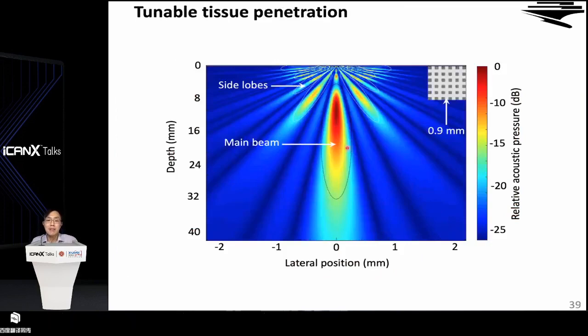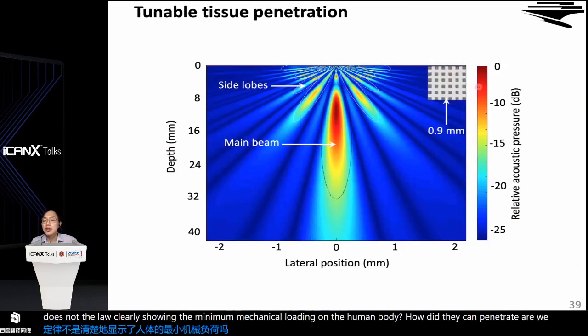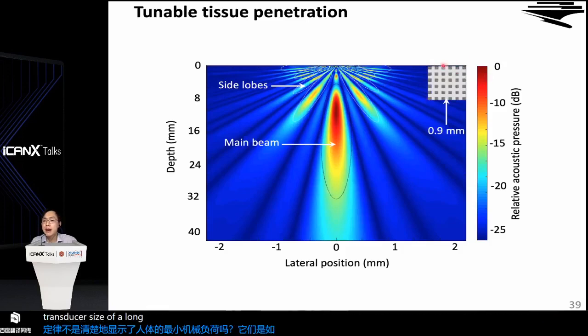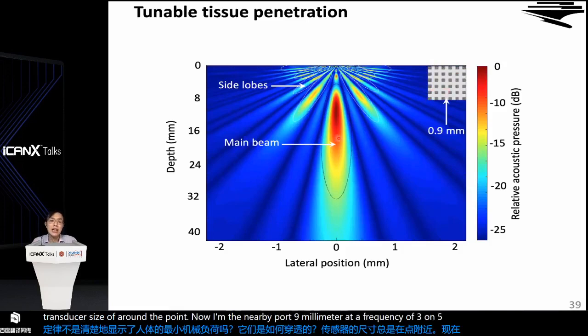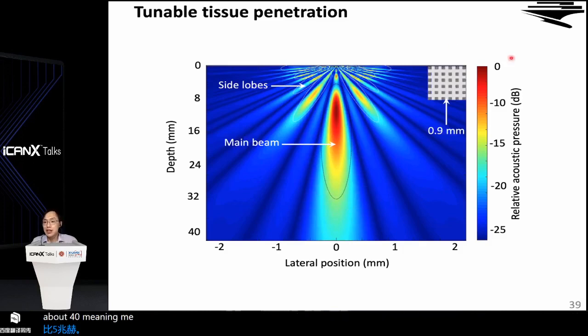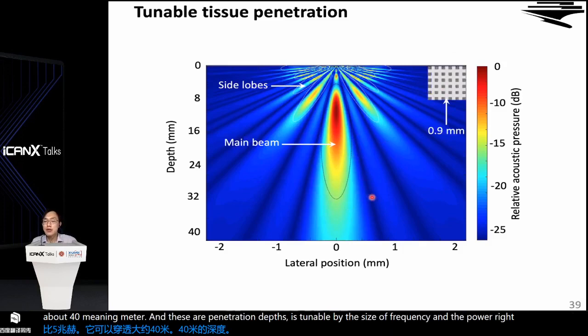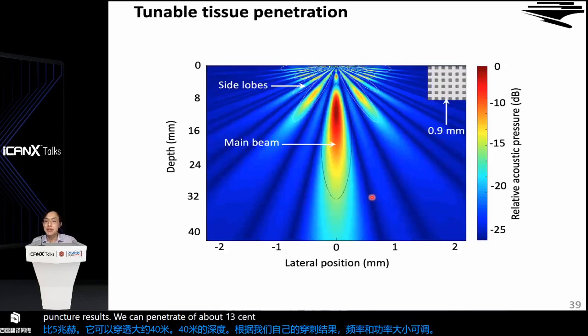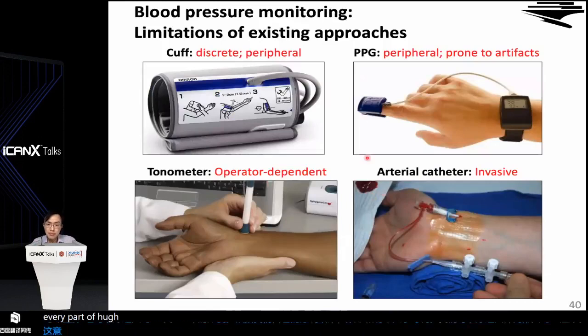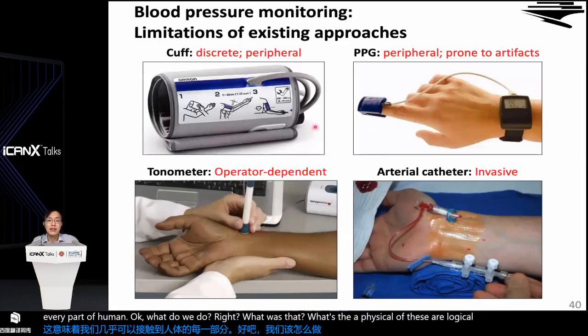How deep can the ultrasound penetrate? With a transducer size of around 0.9 millimeter by 0.9 millimeter at a frequency of 3.5 megahertz, it can penetrate about 40 millimeters. And this penetration depth is tunable by the size, the frequency, and the power, right? In our published results, we can penetrate about 14 centimeters inside the human body, and that means we can have access to almost every human organ. What do we do, right? What physiological signals can we sense?